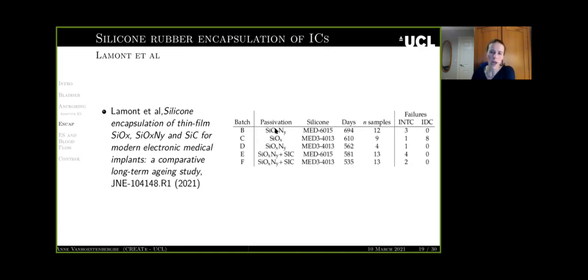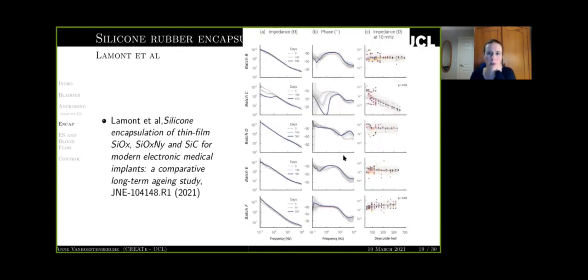In other words, a combination of a passivation layer of silicon oxynitride with or without silicon carbide, protected by either of two types of silicone rubber, gives no detectable corrosion with the most sensitive picometer measurements we could do for a period of two years, under bias in heated water, so in an immersed, heated environment. And this is just to show you briefly the results that we observed. What I mean by failures is not a gross failure. You still can't see the corrosion, but all sensors are extremely sensitive.